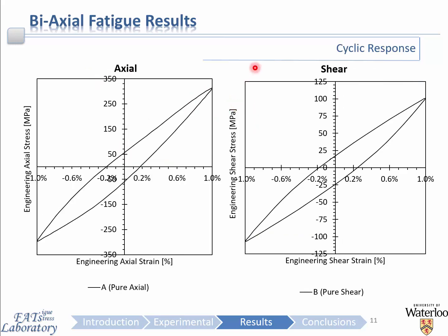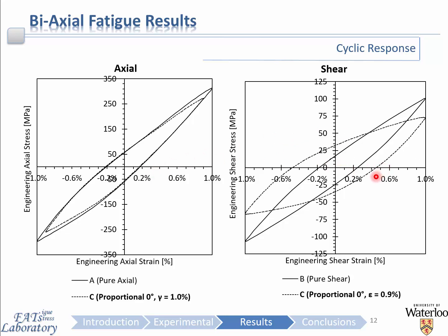Now looking at the stabilized pure axial and pure shear cyclic response for a fully reversed axial strain amplitude of 1% on the left and 1% shear on the right, it can be observed that, similar to the previous slide, there is an apparent asymmetry of the axial response, whereas in shear it is virtually symmetric. Now adding the biaxial proportional loading, which are these dashed lines, it can be observed that the axial response is virtually identical, whereas the presence of the axial strain has dramatically lowered the shear stresses in both directions, the peaks, as shown in the figure on the right here.